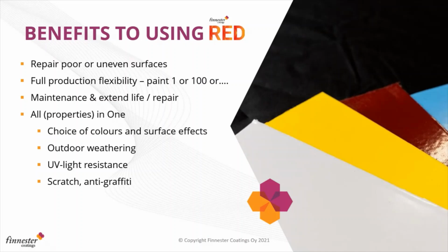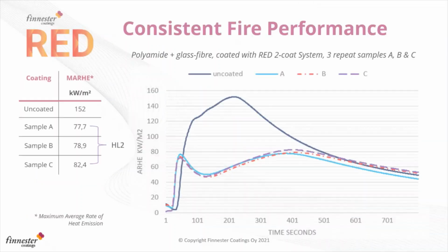And also, you can get all the properties in one. You can have a choice of colors and surface effects. You can have a gloss level. You can have textures. You can have red, blue, yellow, whatever. And you can have outdoor weathering, UV resistance, and hard, scratch-resistant, easy to clean surfaces. These are also decorative coatings. And moreover, maybe the key point here is that it will give you confident, consistent fire and thermal protection, because these are not incombustible coatings, these are fire protection coatings. So they protect the substrate from fire, they keep the heat out of the substrate. So you get very confident and consistent results, as we see here in the next slide.